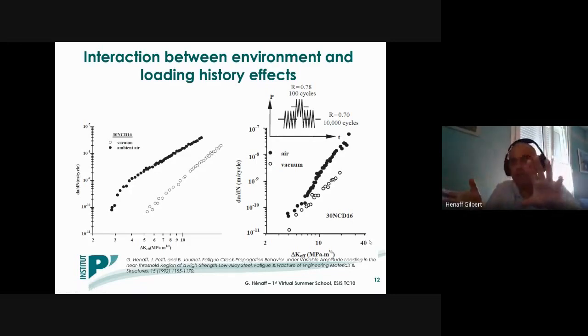So that means that it seems to be the opposite of what is observed under constant amplitude loading, where the maximum enhancement is observed in the low delta K region and tends to disappear at high delta K values. But actually, the analysis of these data demonstrated that, in fact, there is no real interaction between loading history effects, or retardation effects, and environmental effects. What is observed here is just a direct consequence of these differences observed under constant amplitude loading.